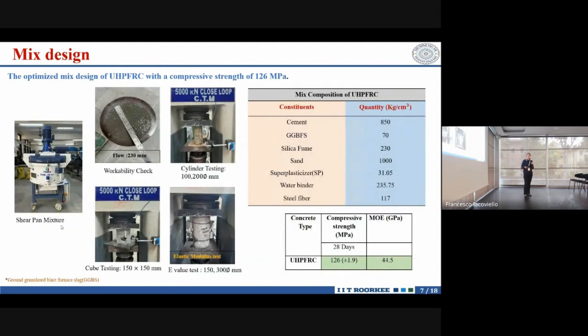So we have used a shear pan mixer to come up with a consistent flowable mix. With the flowability, we are getting 230 mm on the slump table, and we have used cylinder as well as cube specimens to determine the compressive strength, and for elastic modulus we have used cylindrical specimens as well. And this is the composition of my mix, and from this mix I have got a strength of 126 MPa and modulus of elasticity of 44.5 GPa.